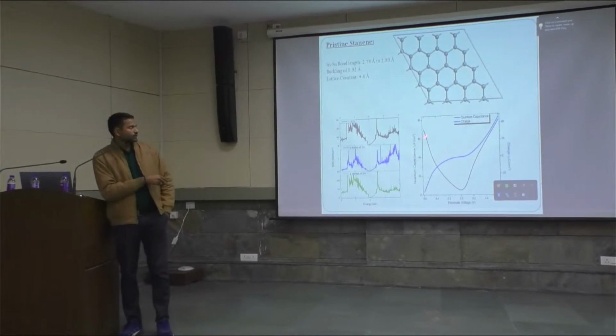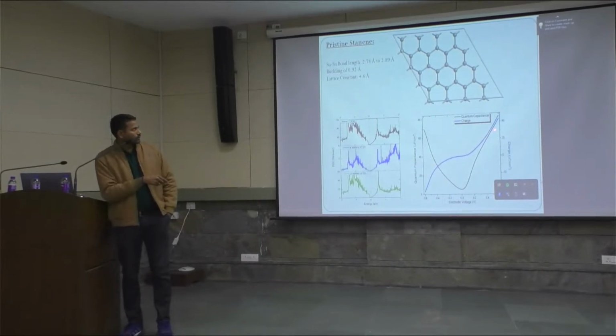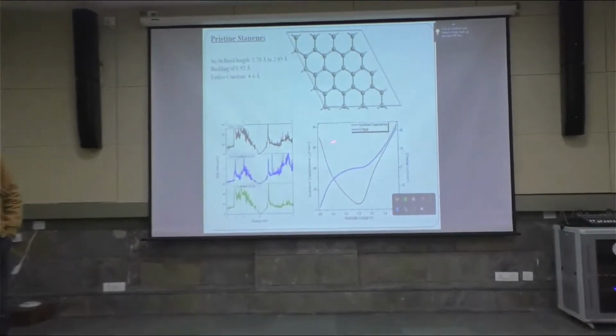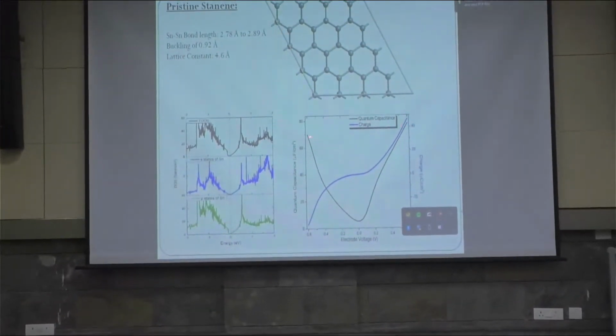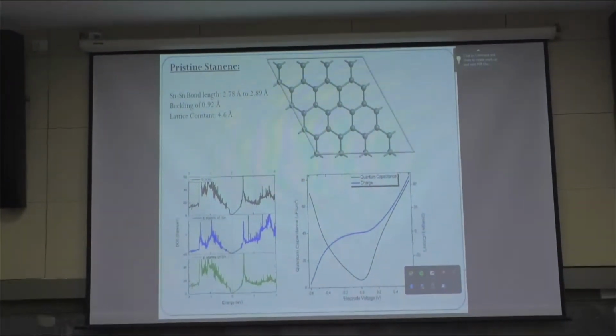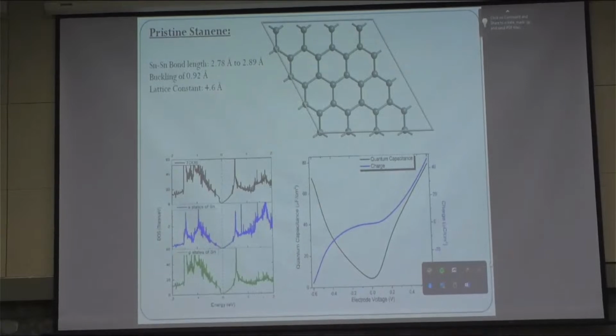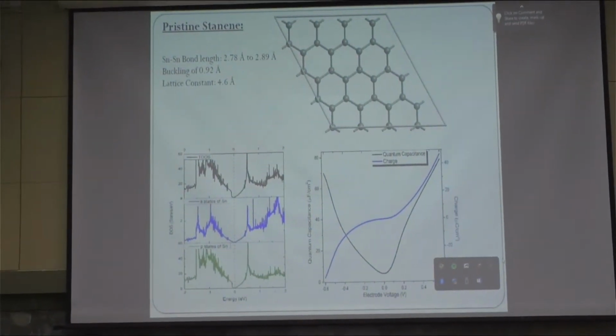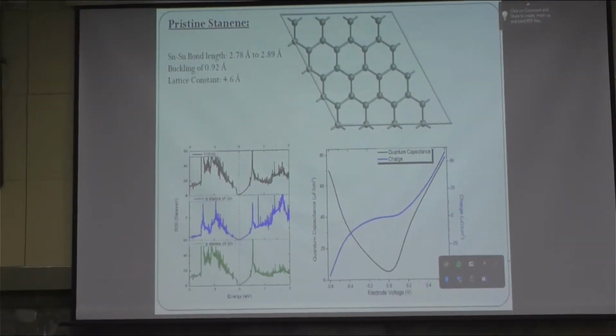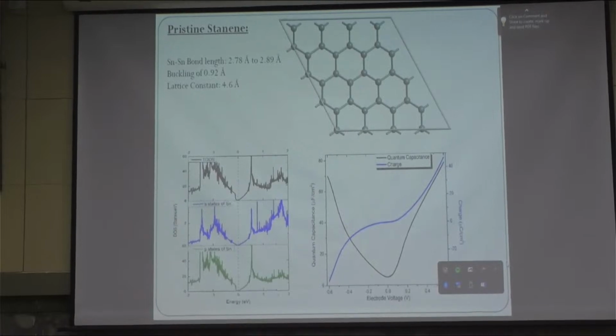And this is the quantum capacitance curve for pristine stanene, and the charge storage curve also. The quantum capacitance offered by the pristine stanene is around 77 microfarad per centimeter square, which is about 7 times higher than the pristine graphene. So stanene offers around 7 times higher quantum capacitance than graphene.